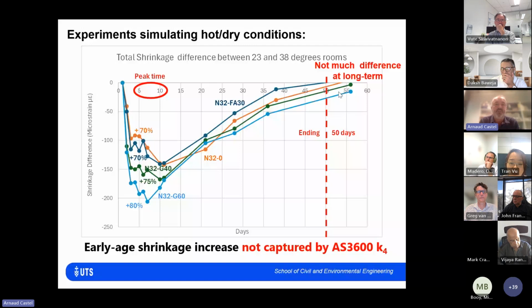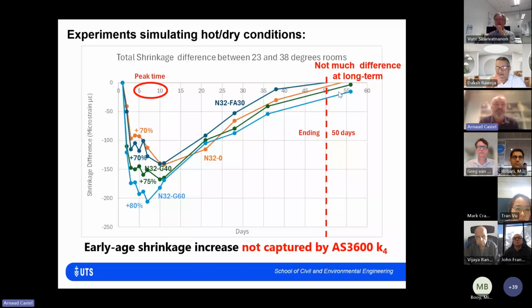And the test is pretty easy, because all we need to do is monitor the strain of the steel ring, and when there is a big drop, that means that the concrete ring is cracking. So we are interested in the time to cracking, and the test is always in the standard condition, 23 degrees, 50% humidity. So I just provide some results here.